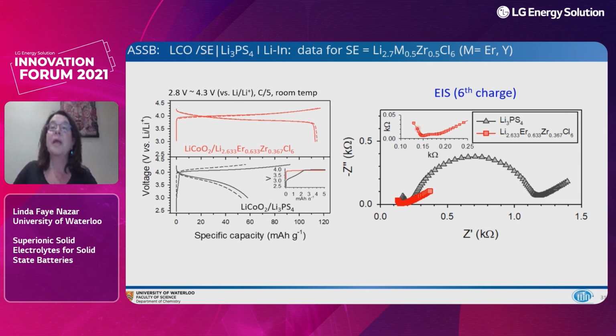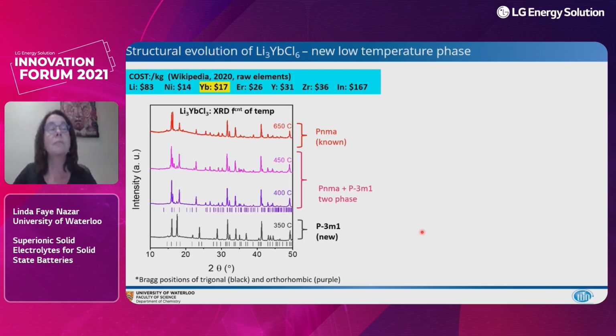Catholyte, and we have versus that where we have the Li3PS4. So in both cases, we have LPS as a separator, but we've swapped out the Li3PS4 for the halide. And you can see that the charge transfer resistance here is reduced from about 950 ohms all the way down to 40. So that's indicative of a pretty good and clean interface. And that's really what gave us a lot of excitement in this area.